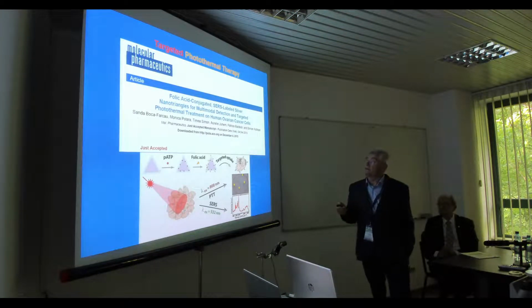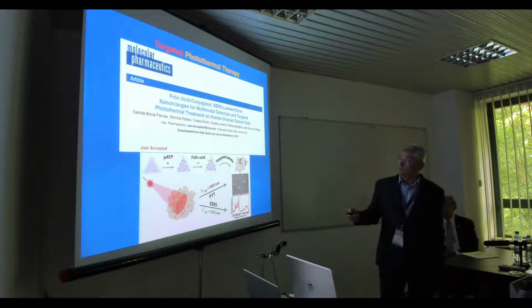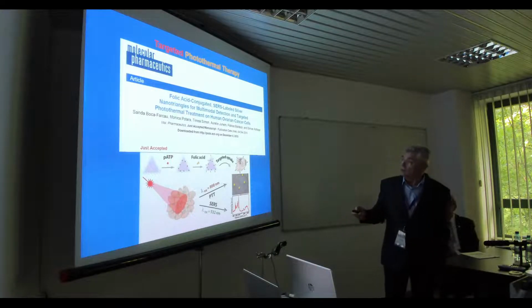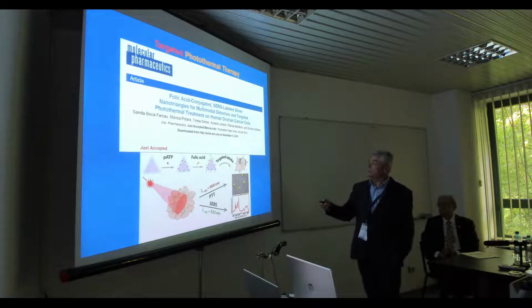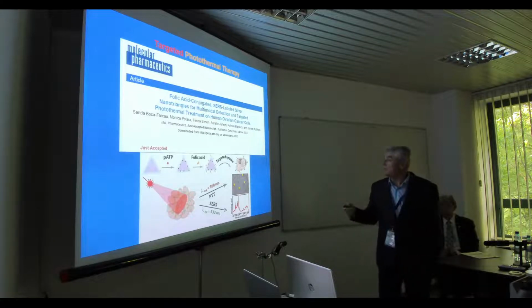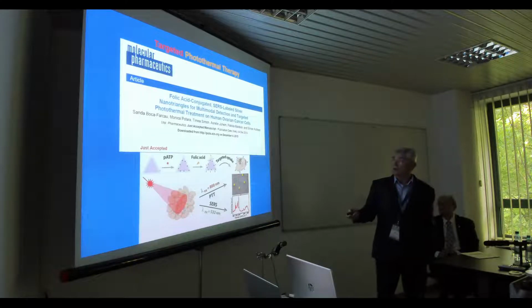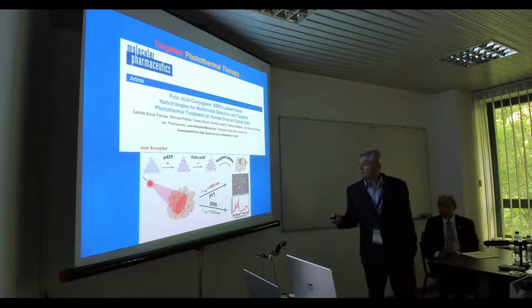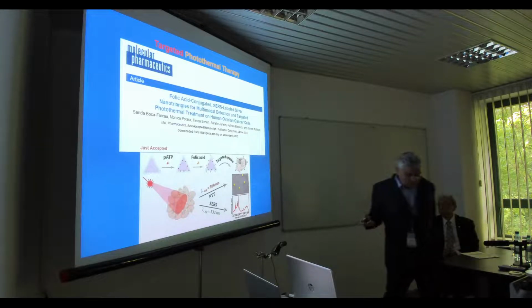By folic acid you address specifically the nanoparticle, the same triangular nanoparticle, with a reporter, para-aminothiophenol, then folic acid to recognize the receptor expressed by the surface of the cell,